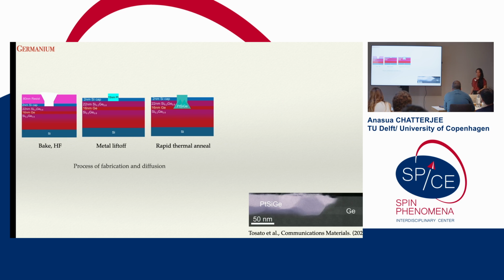And so we do the same thing, and this is the process of fabrication and diffusion. So indeed, you put some resist, then you put your platinum on top, and you anneal it down. And here I've done this annoying thing where I've drawn it diffusing outwards, but here is Giordano's paper where, by doing a cross-sectional TEM, he's shown that actually it pulls inwards, if anything. So this is actually quite good because it means that you're not restricted by your kind of splaying or your diffusion, but you're just restricted by your e-beam resolution, which is nice.